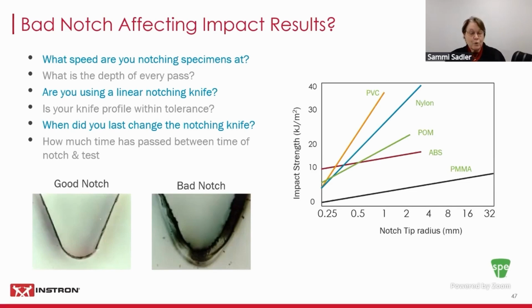Look at whatever tool you're using to cut your notch. Is it within the tolerance? Because the standards do define what the tolerance will be on that notch. So if you're going to cut a notch to a tolerance, is what you're using still within that tolerance? Whatever you're using is going to wear over time. So that comes to when did you last change the notch? The standards define that you should check the quality of the notch. Well, actually, they say you should change the blade or whatever you're using after every 500 notches.